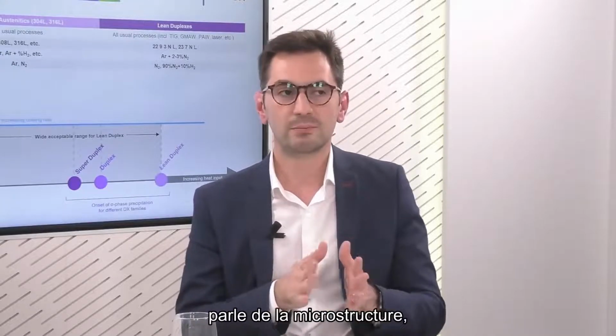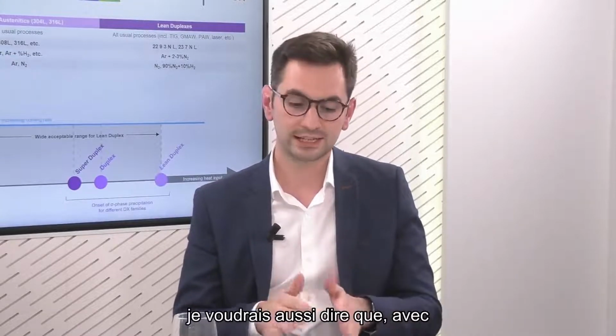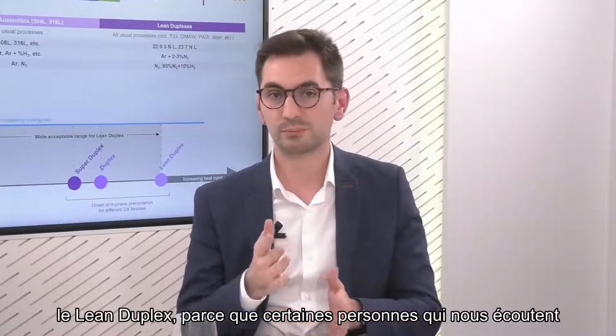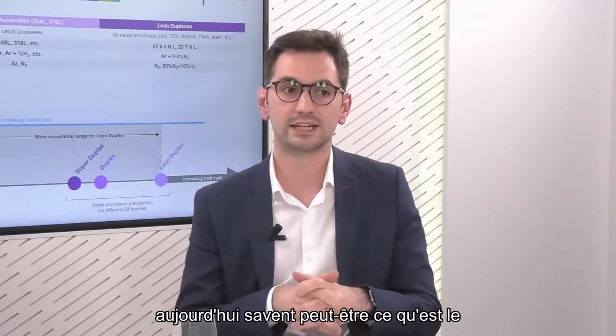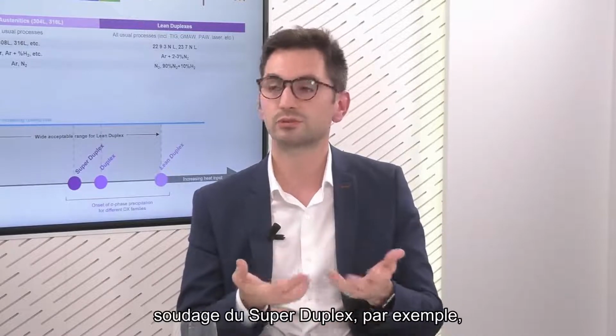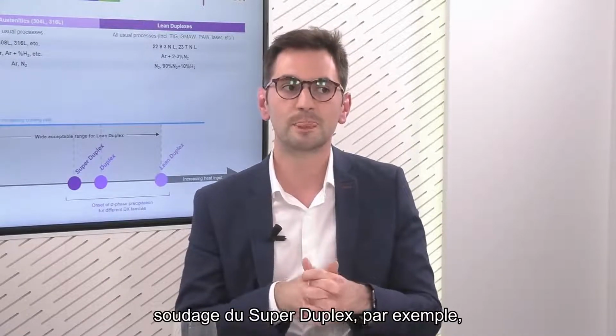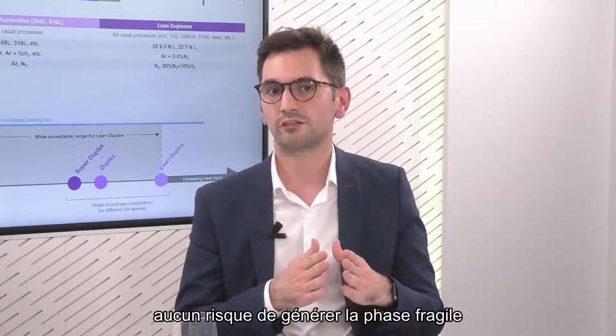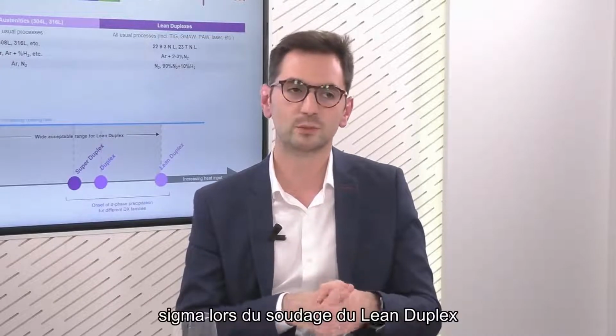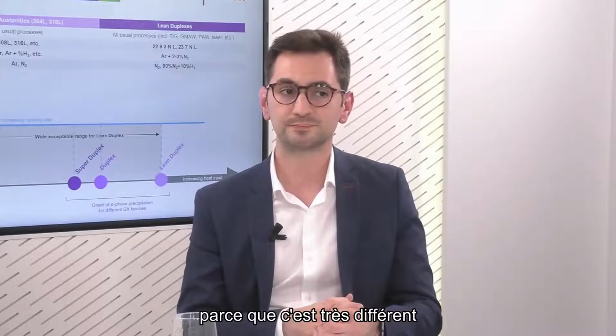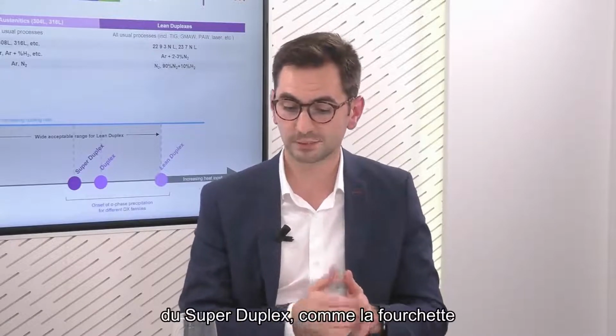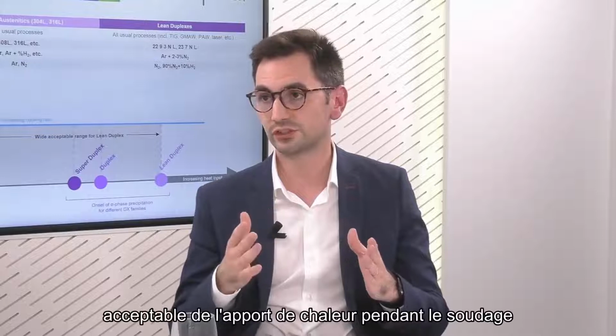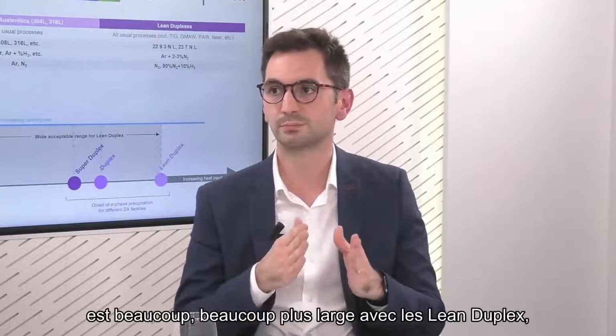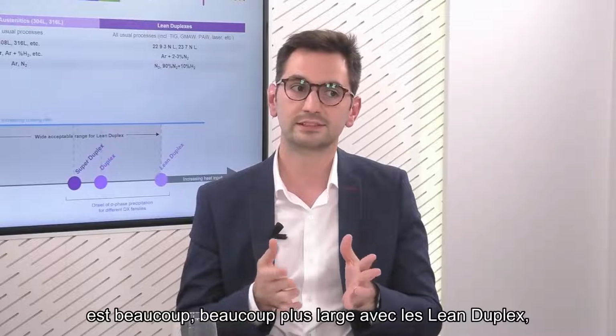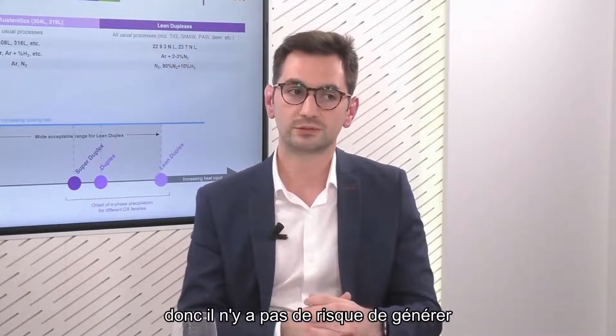And because I'm talking about the microstructure, I would also like to say that with Lean Duplex, because some people listening to us today might know what the welding of super duplex is, for example. There is no risk at all of generating the fragile sigma phase when welding Lean Duplex, because this is quite different from super duplex. The acceptable range of heat input during the welding is much, much wider with Lean Duplexes, and so there is no risk of generating that phase.